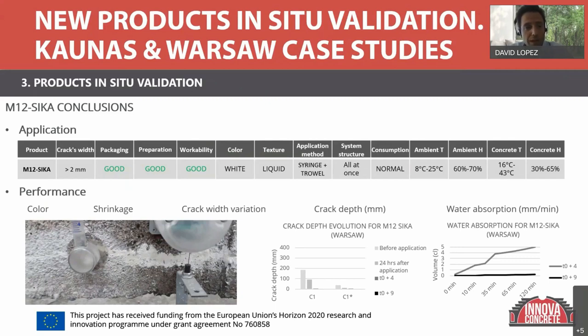So we can conclude that it has good packaging, easy transport, easy preparation, good workability. That means that once you prepare it, the possibility of applying it stays for a long time. It has a kind of liquid texture and is easy to apply. We apply it with a syringe and a trowel. And it has a normal consumption because it's just applying it and filling the crack. It was applied in these ambient and concrete surface conditions, which is also something important to measure in order to make sure that once you validate, you can make a technical sheet of the product indicating in which conditions it works.